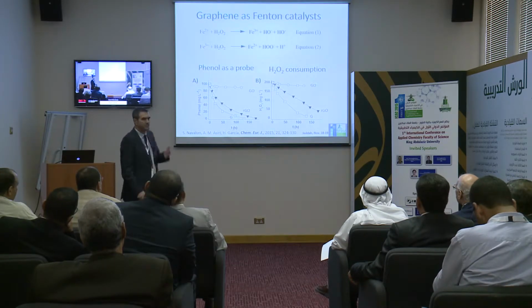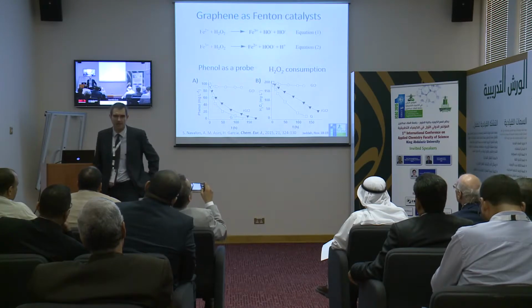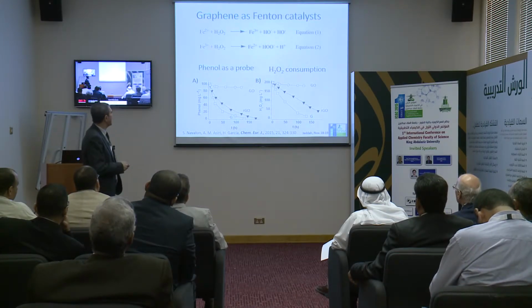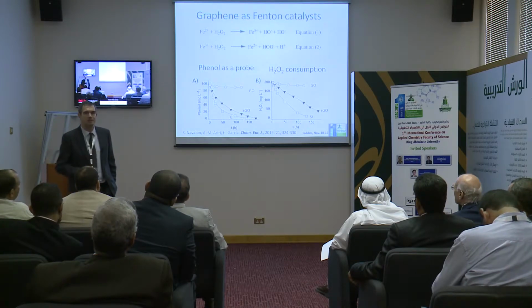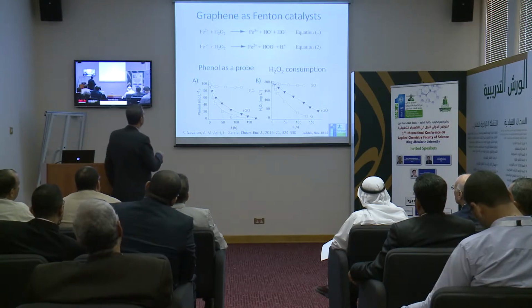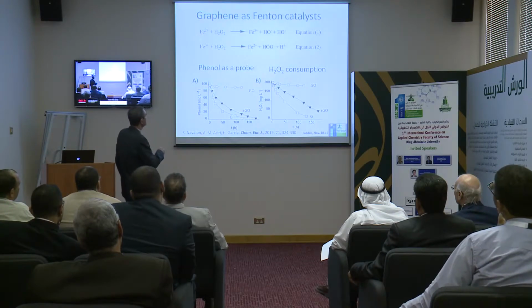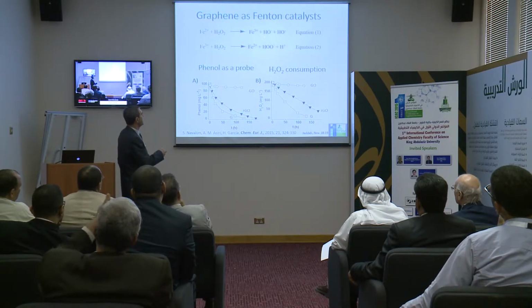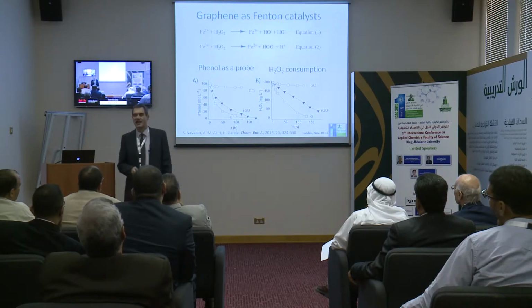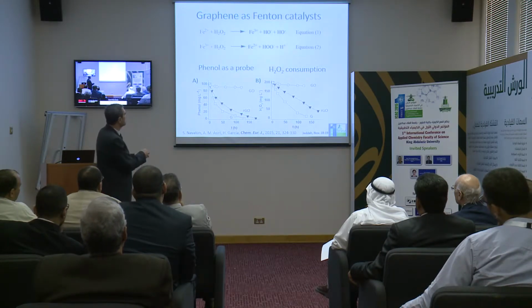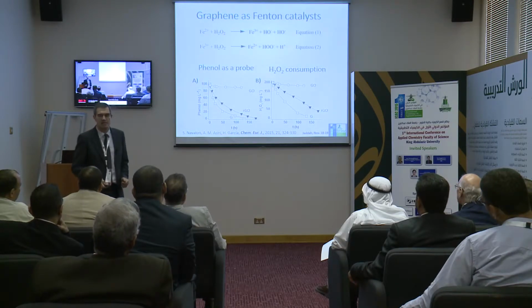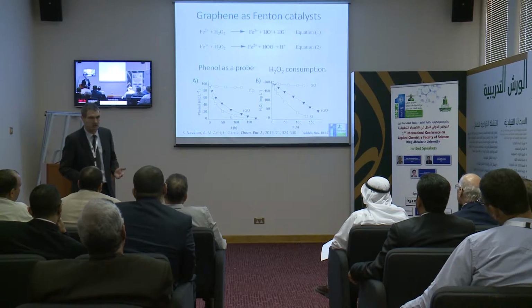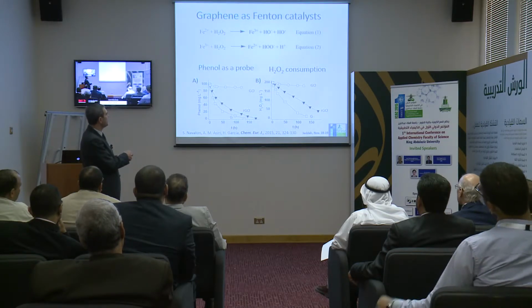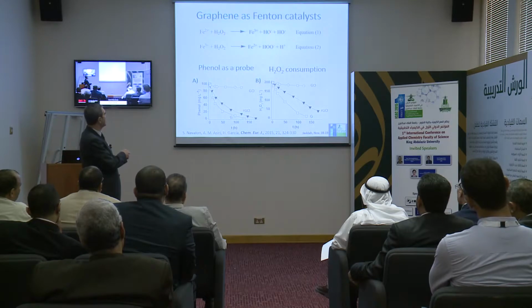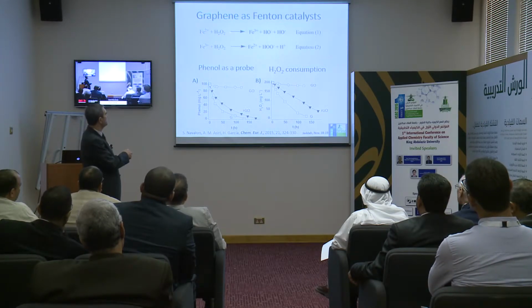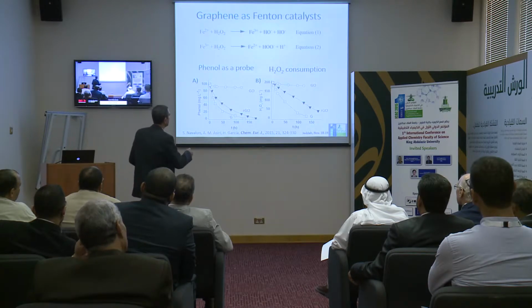Graphene as Fenton catalyst. This reaction is very important for water purification, for the decontamination of water. And this is one reaction that typically has always been reported using metals. The typical metal for this is iron, and iron in combination with hydrogen peroxide, iron becomes oxidized, and the key point of the Fenton reaction is that hydroxyl radicals are generated. Hydroxyl radicals are the most aggressive species that can be present in water. So in water there cannot be anything more reactive than hydroxyl radicals, and using hydrogen peroxide and iron 2, we generate this hydroxyl radical.